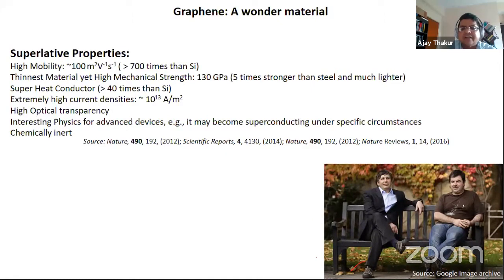And then when properties were measured, extremely fantastic properties, including very high mobility of about 100 meters square per volt second, where you can compare this with silicon. So silicon is about 1/700 times this mobility. This was the thinnest material, but with highest mechanical strength. So this mechanical strength was about 5 times stronger than steel, while this material being much lighter. This was an extremely good conductor of heat, about 40 times that of silicon, and extremely high current densities could be sustained, as high as 10 to the power 13 ampere per meter square. Besides this, graphene also was shown to have very high optical transparency, second only to maybe quartz, and interesting physics for advanced devices. For example, it may become superconducting under specific circumstances.